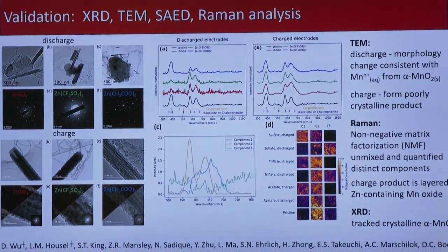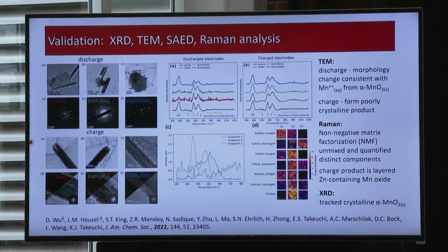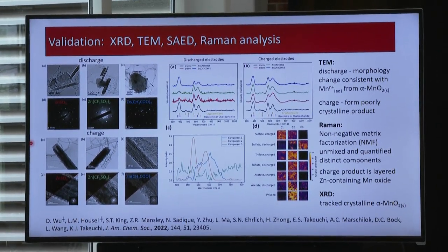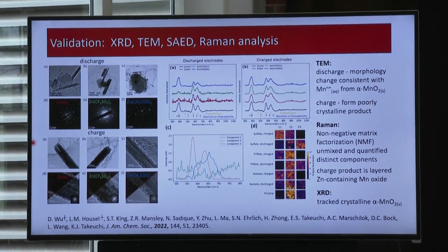In conjunction with our X-ray absorption spectroscopy study, we used X-ray diffraction, transmission electron microscopy, selected area electron diffraction, and Raman. And this is just a comment, perhaps more to the graduate students and students than to the faculty, because I'm sure the faculty already know this. When you're dealing with a very complex system, often having multiple characterization methods is necessary. Because if the multiple characterization methods all end up pointing in the same direction, then we have much more confidence that what we've identified by a single characterization method is representative of what's happening for the entire system. So we found that spectroscopy, diffraction, and microscopy all led us to the same conclusion, which was certainly gratifying.